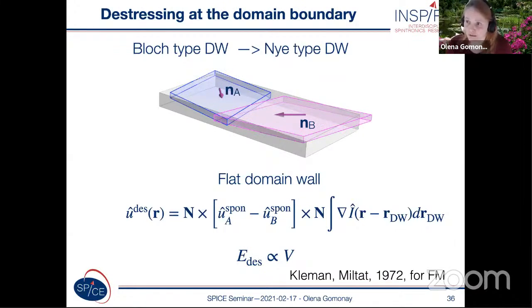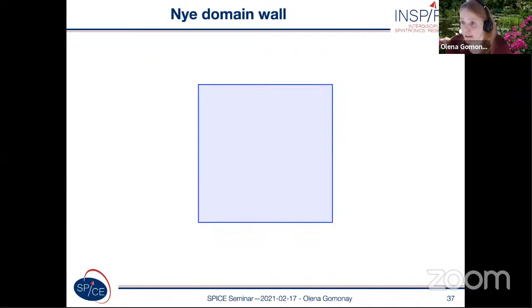Also, we can find a similarity between the Bloch and Néel walls in ferromagnets and different types of the domain walls in antiferromagnets. In ferromagnets, Bloch walls are believed to have lower energy because they are not associated with magnetic charges, and Néel walls produce this divergence of M and charges. And the same can be applied to the antiferromagnetic domain walls. In this case, it's called Nye walls, the walls which do not have any incompatibility. And this concept was first introduced also many years ago by Kleman and Miltat in application to ferromagnets, but we can also use it for antiferromagnetic materials.